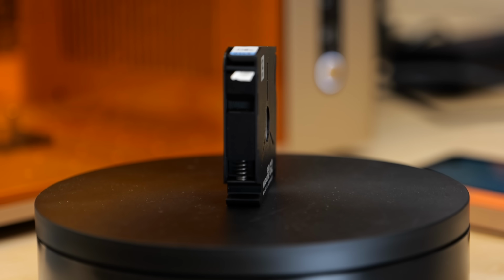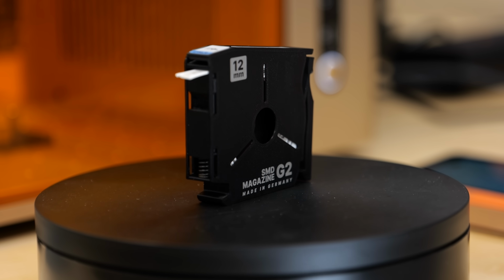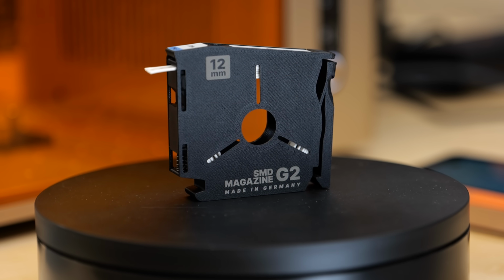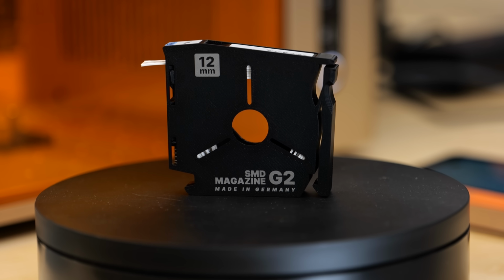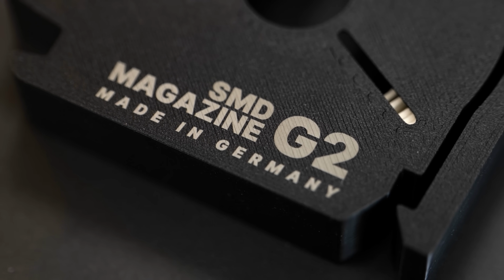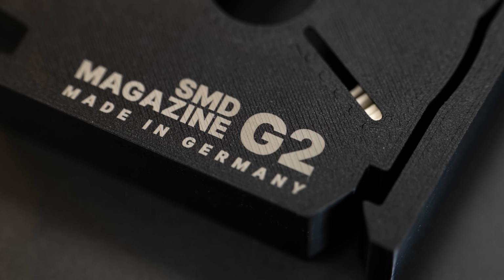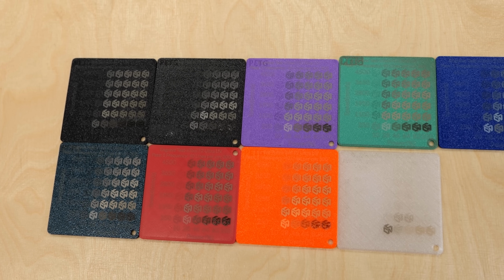Out of curiosity, I also printed 2 magazines in black PLA and engraved those. And there, especially with the UV laser, the results looked amazing. The marked area turned almost white and had very high contrast. And that really summarizes the whole topic.